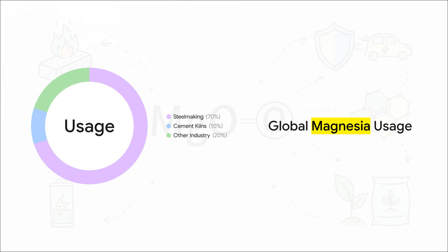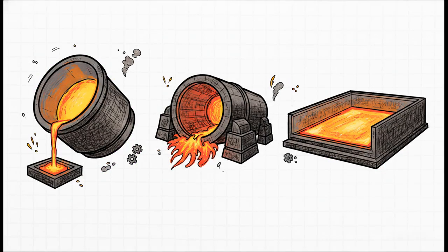And this really brings us back to that microscopic basicity we discussed earlier. In basic oxygen furnaces, MgO perfectly resists the aggressive iron oxide-rich slags that make mass steel production possible. In cement rotary kilns, it survives harsh alkali vapors and dusty calcium silicate melts without even flinching. In glass float tanks, MgO blocks maintain the furnace volume against highly corrosive lithium, sodium, and potassium silicates. Its chemical resistance is quite literally the bedrock of our global infrastructure.